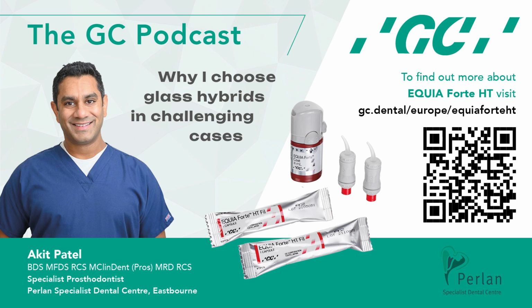The second approach, obviously, if we're unable to reverse the caries, then we'd have to intervene with an operative restorative approach, which would include removal of the caries, either fully or partially, and then restoring the cavity with either a high viscosity hybrid glass ionomer like Equia Forte HT or a composite like G-ænial Universal. However, root caries doesn't always appear to make it easy for us, and classically they start interproximally, extending subgingival. So we want a material that we can work in such environments where we can't isolate with a rubber dam.